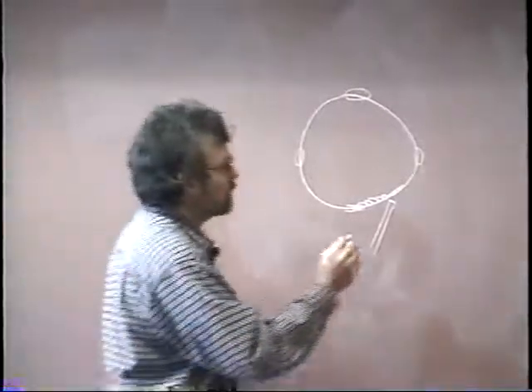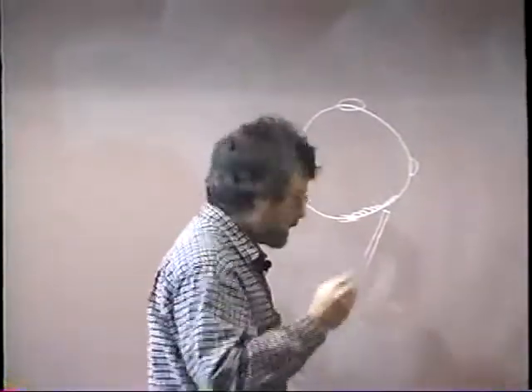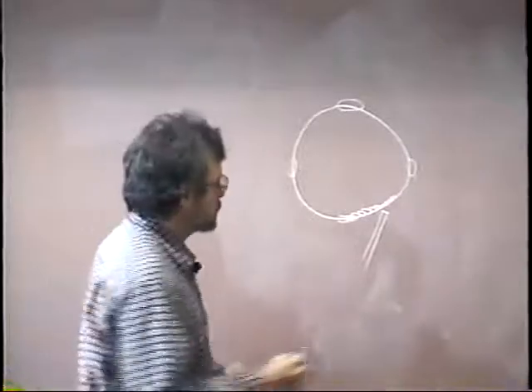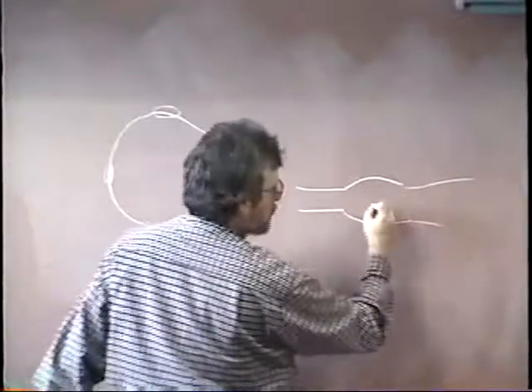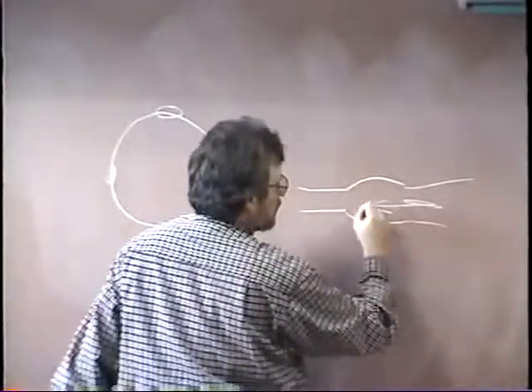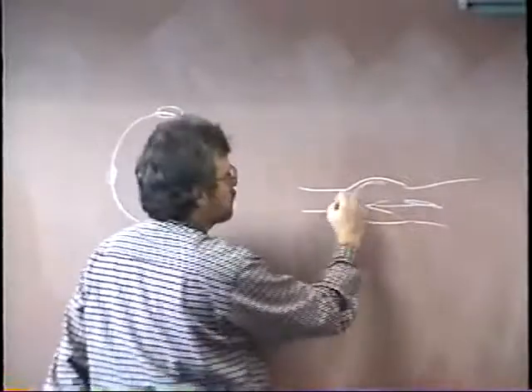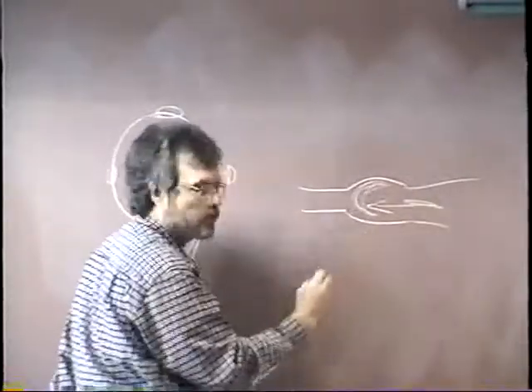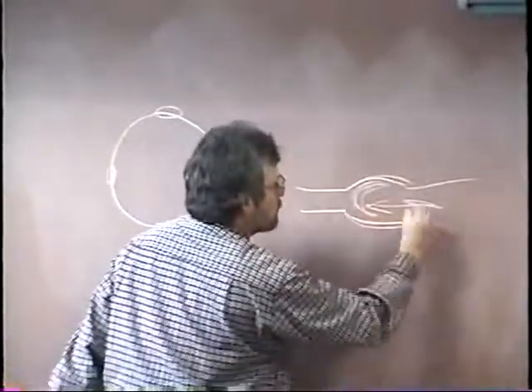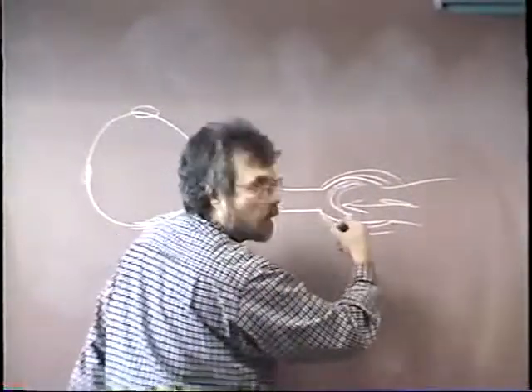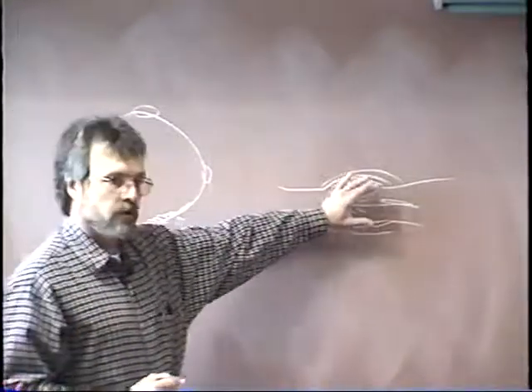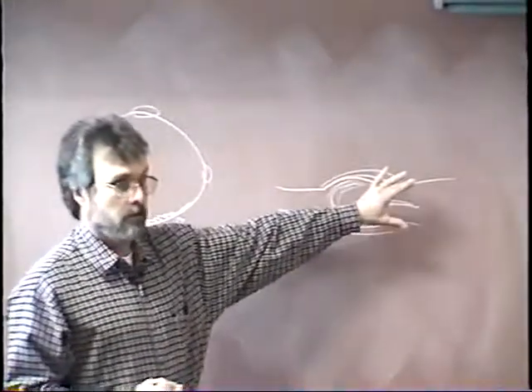The other thing you can do is you can go to that whip. If that keyhole starts to get too big on you, if it starts to open up, what you can do here is start whipping and whip it straight out and straight back. Don't try to chase a keyhole from side to side. If you try to chase a keyhole from side to side, you're simply going to concentrate that heat and that keyhole is going to get bigger. But you want to whip it out and back, pause, whip it out and back, pause, and that will allow that keyhole to close up for you. And try this because it really does work.